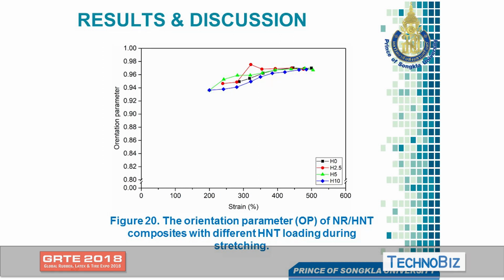Depending on the orientation parameters over here, we will study further whether we can make a relationship with our findings or not. Because this result is not so significant yet. But the most interesting thing over here is that once we put in the higher amount of filler at 10 PHR, the orientation parameter is lower than with other additions of HNT, assuming that agglomeration is there. Once the aggregation is there, it changes the alignment of the stretching of the molecular chains.